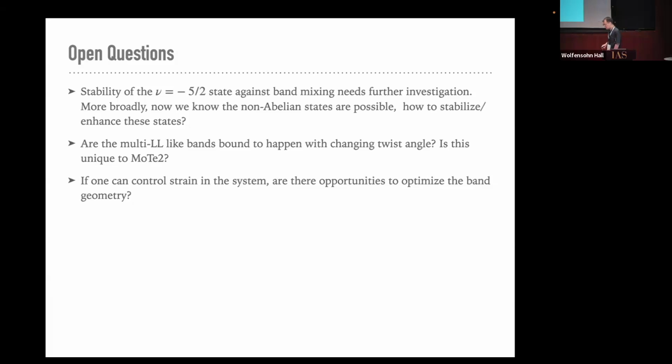And finally, as I showed you earlier, this entire band structure is driven by the competition between piezoelectricity and ferroelectricity, of which the former can be controlled by strain. So experimentally, if you can build a device where you can actively and accurately control the strain of the system, that offers engineering opportunities to optimize the band geometry.